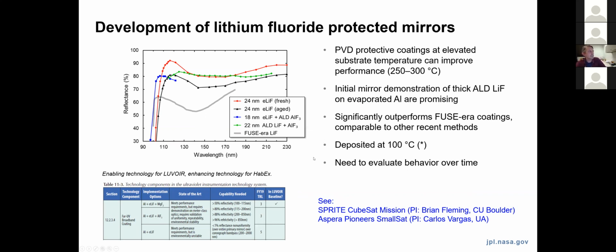Aside from mag fluoride, there's been a lot of recent interest in lithium fluoride as a protective coating material. This enables you to operate below the short wavelength cutoff of mag fluoride, which is around 120 nanometers. Lithium fluoride has been used on previous NASA missions as a protective coating material. The FUSE mission used lithium fluoride on aluminum for the reflective coatings in two of the channels on that instrument, in order to achieve performance really only in this 90 to 110 nanometer wavelength range. You can see that at the time that the FUSE mirrors were fabricated, there wasn't a good understanding of how to achieve high performance out of the lithium fluoride itself. So although the short wavelength performance could be improved over something like mag fluoride, it was really only at modest reflectivities, 60% or so, with correspondingly low reflectance, even at longer wavelengths.